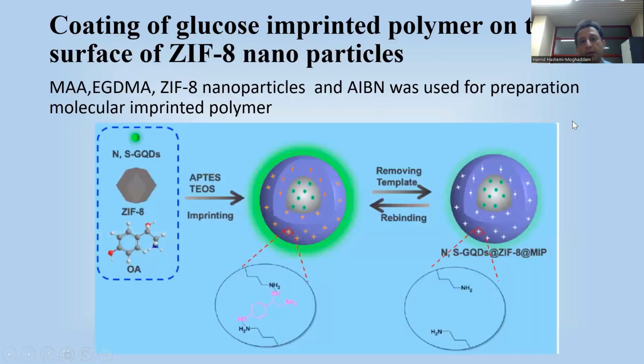In the next step, on the surface of this ZIF-8 nanoparticle, a polymer coating is synthesized. For synthesis of the polymer coating, we use methacrylic acid as monomer, ethylene glycol dimethacrylate (EGDMA) as crosslinker, ZIF-8 as core nanoparticle, and AIBN as initiator of polymerization.